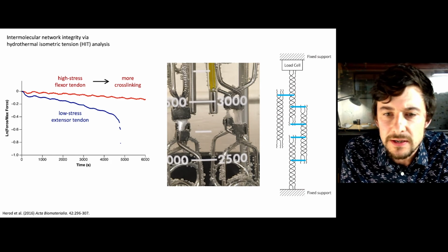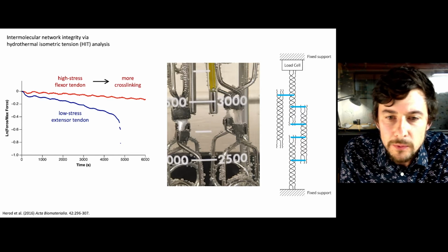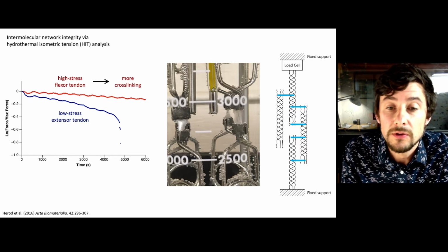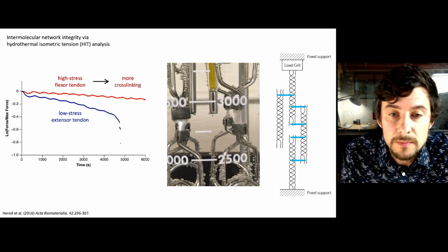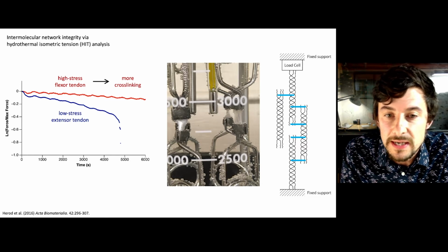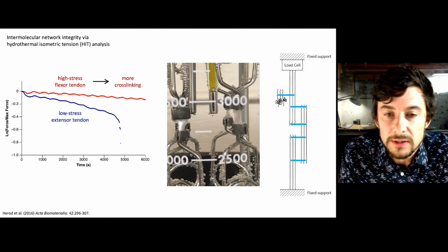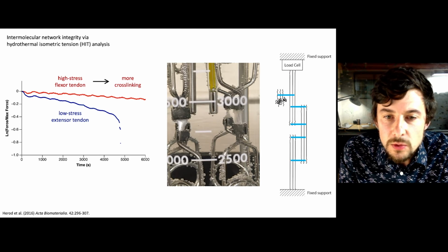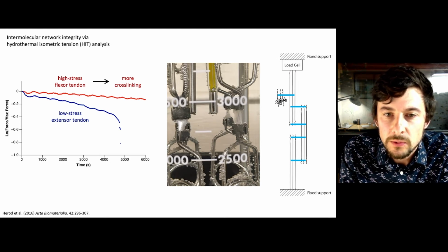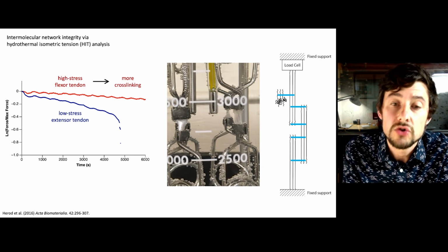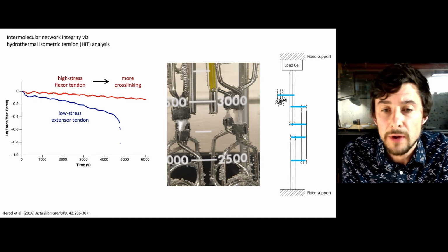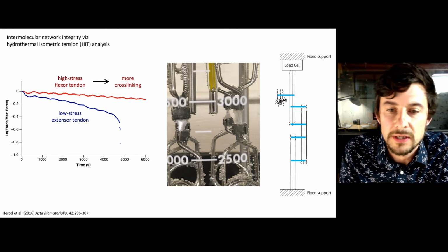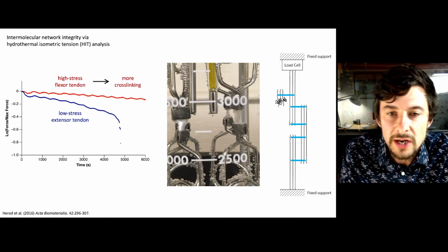When this is placed in hot water, at some point those triple helical collagen molecules will rupture the hydrogen bonds holding the alpha chains together, and they will denature. And when those three alpha chains separate in each of the molecules, the alpha chains are entropically driven to coil randomly, but are prevented from doing so by their isometric constraints, so they will generate measurable tension.